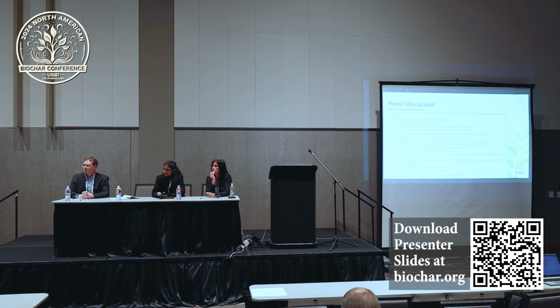and so there's been some work, but this is something we're currently trying to figure out with uranium. And uranium is special because it has all sorts of oxidation states in water, and those oxidation states will probably stick differently to different chars under different pH conditions, different co-ions, etc. So I'm going to say it depends, and I'm not completely sure what it depends on yet.